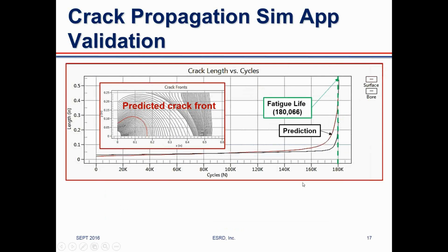We have gone through an extensive validation process. Here is one result of a validation test. The prediction is indicated by the two curves, the red and the black, that represent the two crack fronts. And this is the actual fatigue life where the specimen failed during the test.